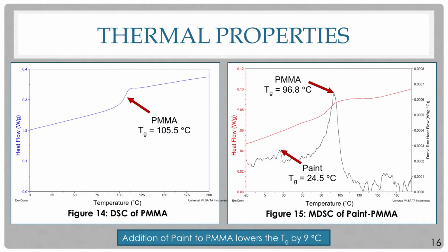Using DSC, we determined that the glass transition temperature of PMMA alone was approximately 106 degrees Celsius. However, in the blend, the glass transition temperature of PMMA was decreased by approximately 9 degrees Celsius. The second peak, labeled paint in figure 15, is the glass transition temperature of the paint in the lower temperature range.